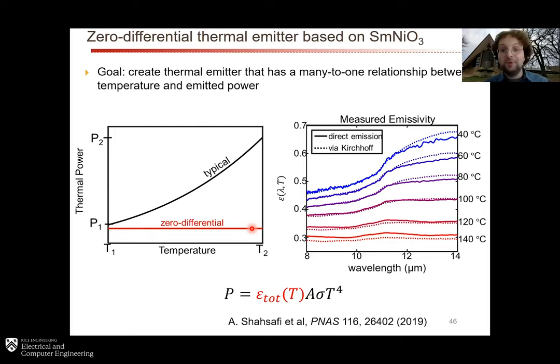Fortunately, we've been able to implement this using a thin film of about 150 to 200 nanometers of samarium nickel oxide on a sapphire substrate. And here is an experimental measurement. This is the emissivity versus wavelength versus temperature measured a couple of different ways. The measurements are not quite as perfect as we have now because they were done before we figured out all of the final details of our thermal emission measurements, but still they're quite accurate. And you can see that the emissivity decreases gradually as a function of temperature.